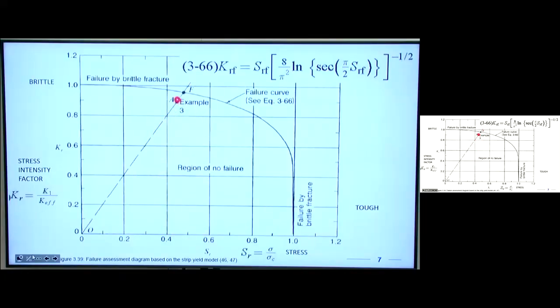If the load continued to increase, however, and we took that into account, then we would eventually get up to this point here on the line that we drew from that strip model. And the difference between where we are and where we would experience failure gives us an idea of a safety factor. So how much below this failure load are we? In order to calculate that, we could go up and see at what x and y we would expect to get failure, and then divide by the distance to that point there, which we already know.